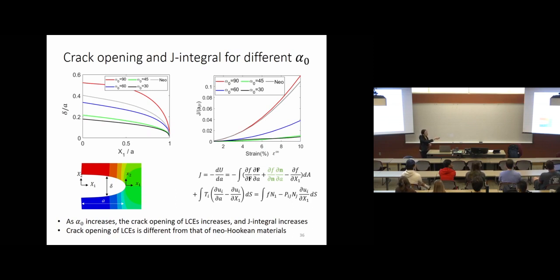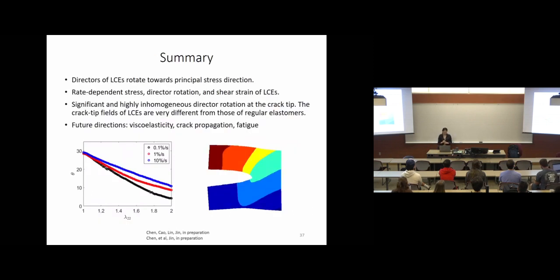And indeed, consistent with the crack opening, we observe when you have larger alpha naught angle, the J integral is higher, which means there's more energy to be released in the material when the crack is propagating. You have a large driving force for the crack propagation. So let me also summarize this part.